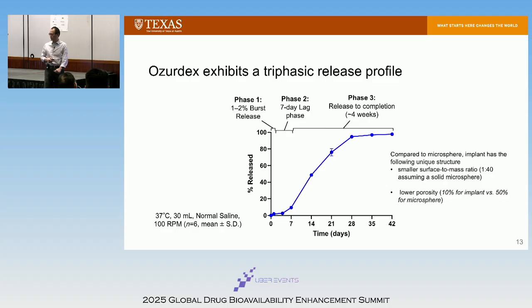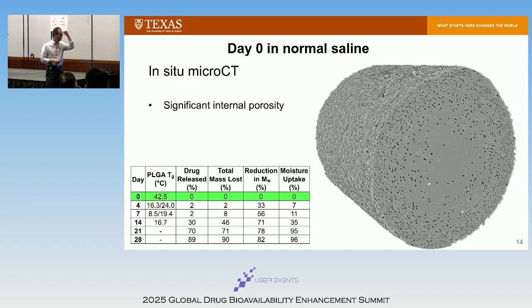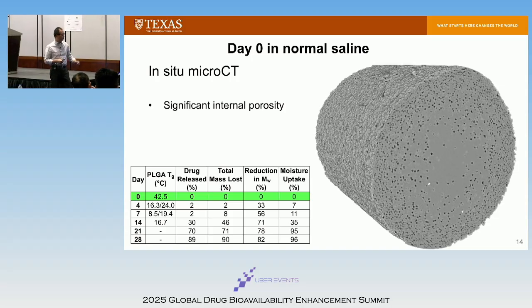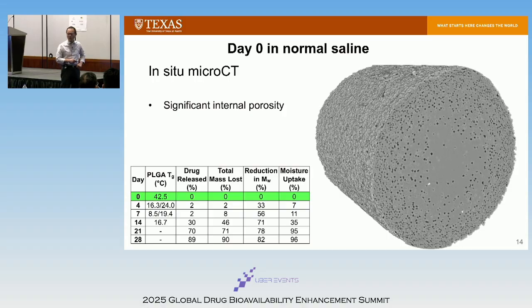But so why does it release drug this way? So we did this whole test, and we monitored several things, right? We monitored the PLGA Tg, wet Tg, okay? We looked at the drug release, the weight loss, polymer molecular weight, how the polymer degrades, and also moisture uptake. So if you look at this table here, we go through day 0 to day 28, right? You find out, even at day 7, we already lost 56% molecular weight. But drug release is only 2%. Right? Even though PLGA degraded, the drug is not releasing.